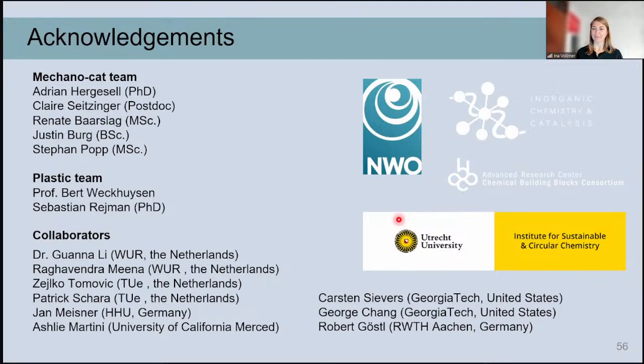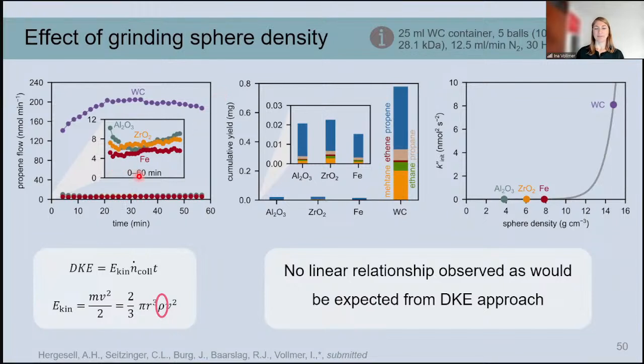We have a few questions from the audience. First, how generalizable are the results that you've shown with zirconia to other materials? So we have, of course, tried to get this more encompassing relationship with these kinetic relationships based on the Zhurkov model. So we have tried here several materials, and it seems that if we just look at the mechanochemistry itself, then the density of the grinding sphere seems to be most important in looking at the activity. And so that could also be a hint at designing other materials in the future, because we could have, of course, another core than the catalytic functionalization that we use.